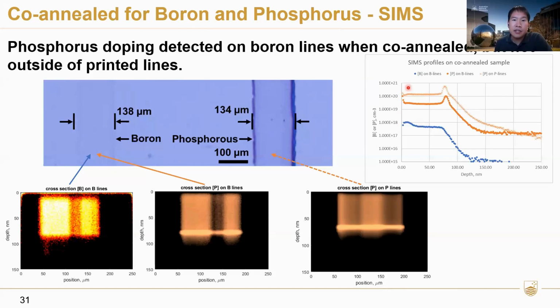But if you look at the SIMS profile here, this is calibrated concentration. The boron is this about 1E18 line here, while the phosphorus on the boron line is not as high as the phosphorus on the phosphorus lines, but still actually higher than boron. So what this suggests is that this boron line is very likely compensated by phosphorus, and therefore it's mostly phosphorus doped.